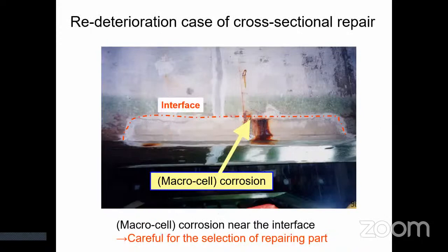Here, I explain notes on the cross-sectional repair method. After application of cross-sectional repair, re-deterioration occurs in some cases, like this picture. Steel corrosion occurred near the interface between the filling materials and the original concrete. This type of corrosion is often called macrocell corrosion.